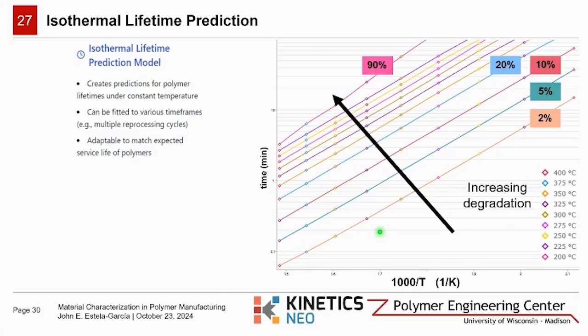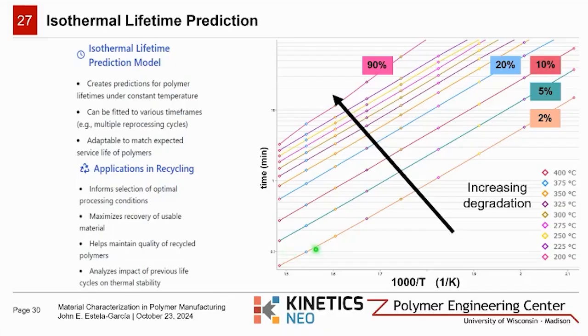In the current case, by predicting how various pyrolysis conditions affect polymer degradation, we can design more efficient and targeted breakdown processes. In the context of mechanical reprocessing, applying this type of modeling to TGA data in an oxidative environment helps us inform the optimal processing conditions that minimize degradation when exposed to air. By understanding how temperature and time affect polymer degradation, we can maximize the recovery of usable material while maintaining our quality. And this is particularly valuable when dealing with recycled polymers, where previous life cycles have already impacted thermal stability.